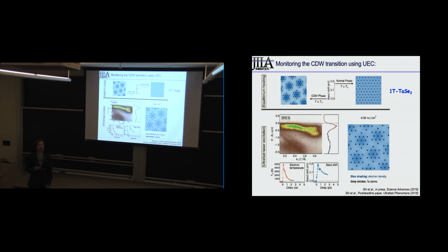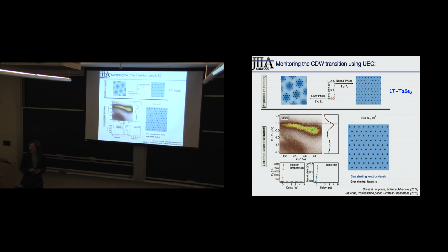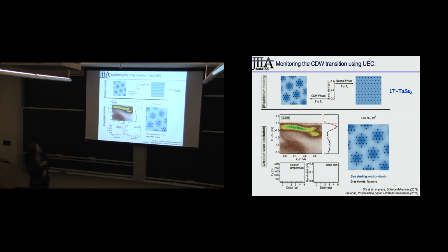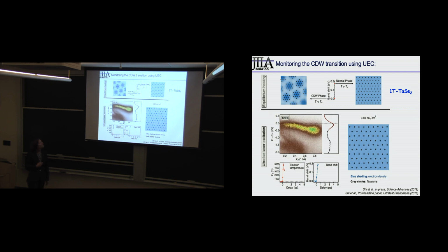So I'll talk about this charge density wave system only because I think it's a selenide system, so it might be something we could actually collaborate on, from what I know that you can make on the MBE. And so this is a tantalum diselenide 1T that normally would either be in an insulating or metallic phase. And you know from the order parameter by the band shift that it shifts up by almost 0.2 in eV when you heat the material or if you shine an ultrafast laser pulse on the material.